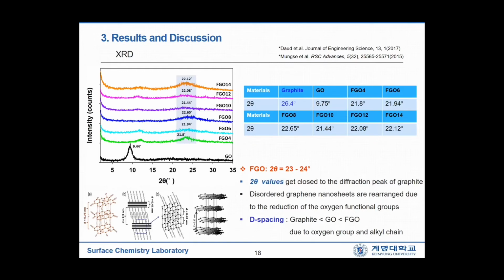As you can see in the table, these spacing values increase in the order of graphite, graphene oxide, and functionalized graphene oxide, due to the oxygen groups of graphene oxide and the alkyl chains attached to the FGO samples.